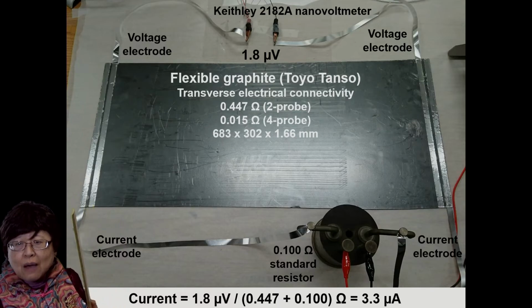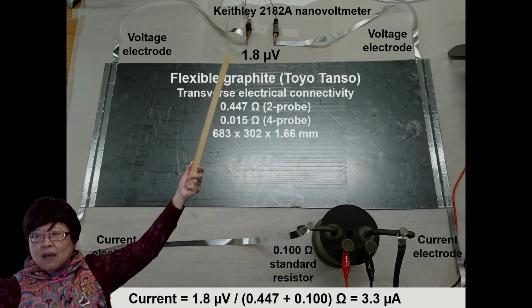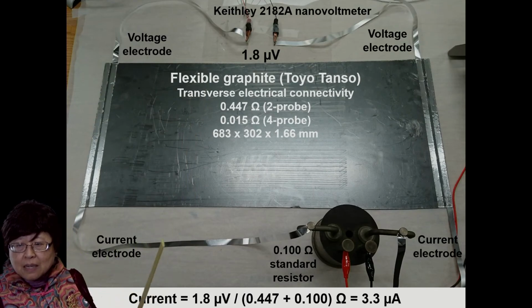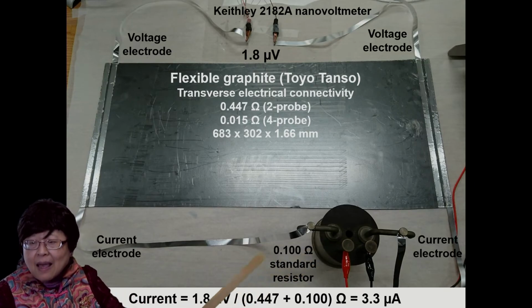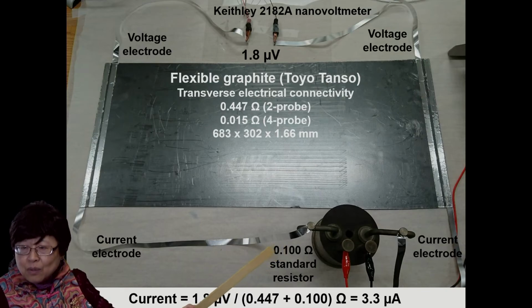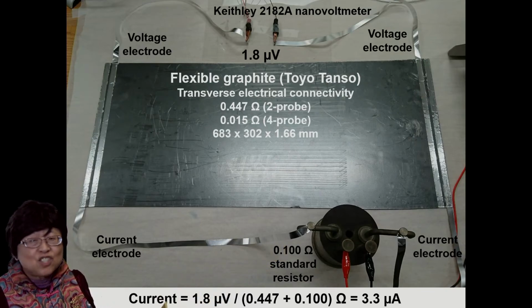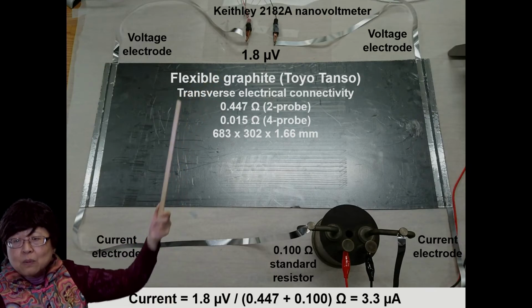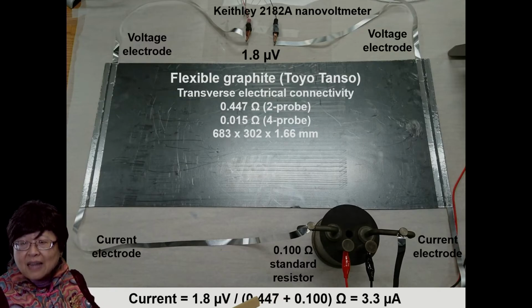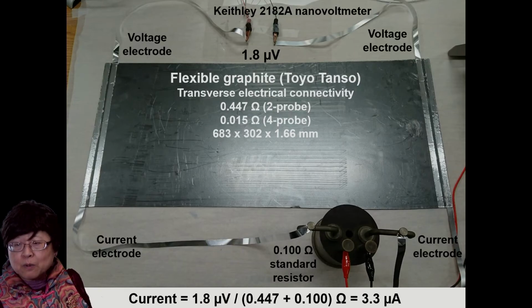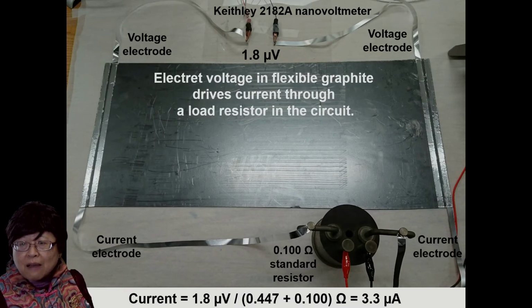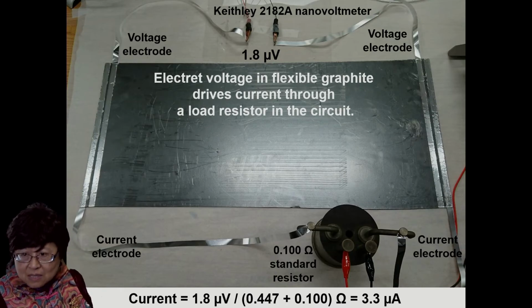And we have 4 electrodes, the 2 outer ones for current and the 2 inner ones for voltage. And we measure the voltage between the voltage contacts using a nanovoltmeter. And we hook up to the current electrodes a load resistor. And indeed, current goes through this load resistor, and the current level is just as expected, being the electret voltage divided by the sum of the load resistance and the resistance of this piece. To be exact, the 2-probe resistance of this piece of flexible graphite. So the electret voltage in flexible graphite drives current through a load resistor in the circuit. And we've confirmed that with different values of the load resistance.